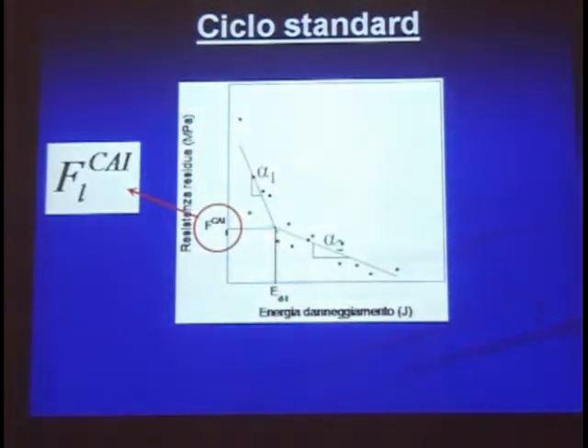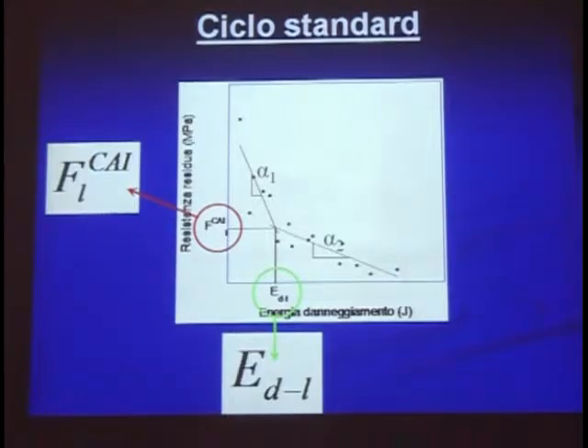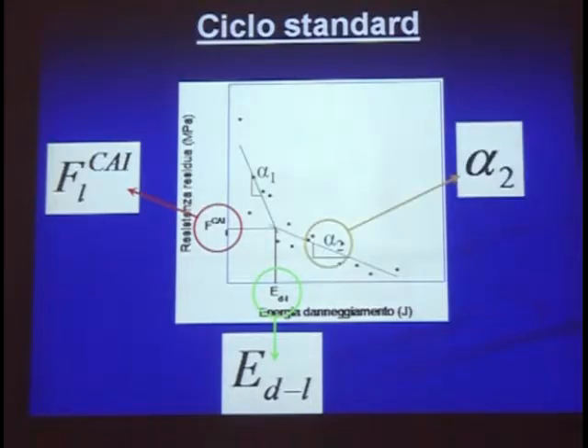So we decided to define some critical points on this bilinear plot. One is the critical strength at transition between one mechanism and the other, which is called FCAI. The second is the critical energy corresponding to the very same value of the critical strength, and then the slope of the second part of the curves, which gives you an idea of the ability of the material to withstand damage when the damage is already significant.